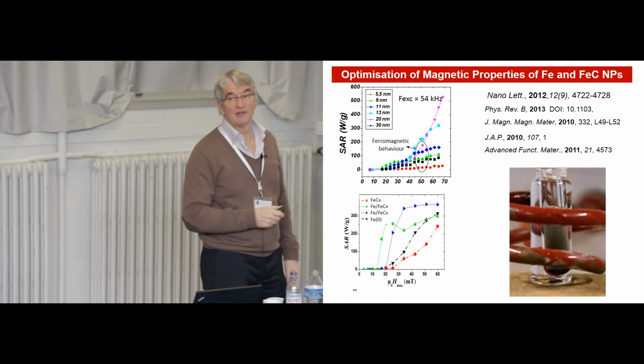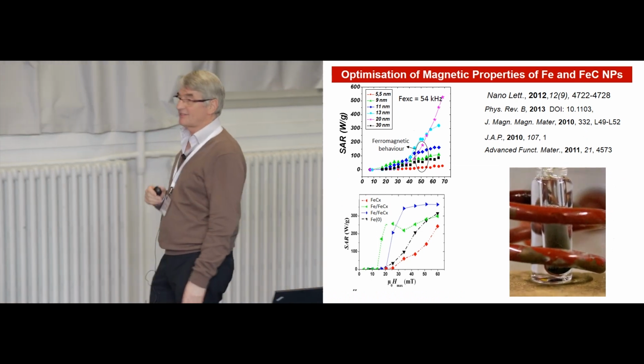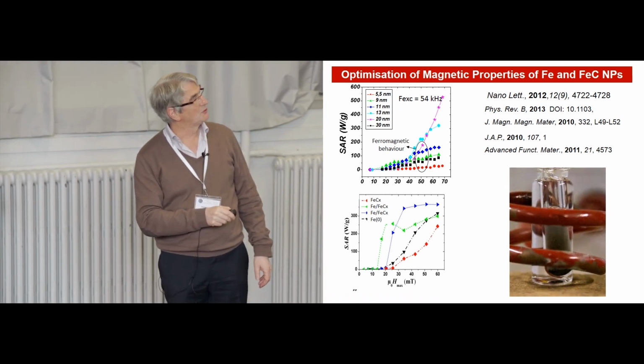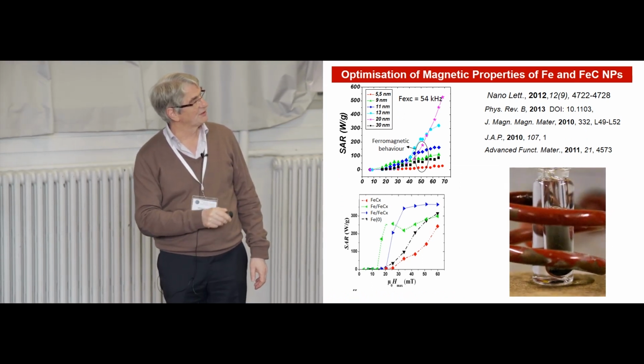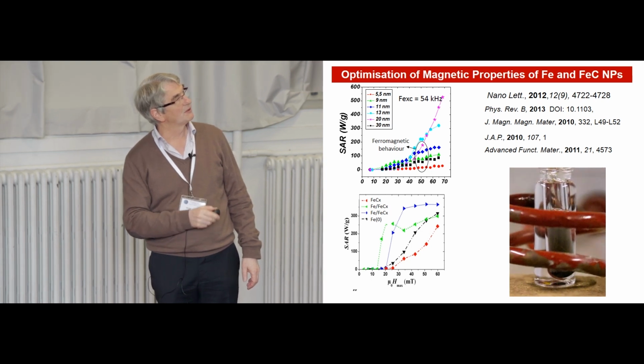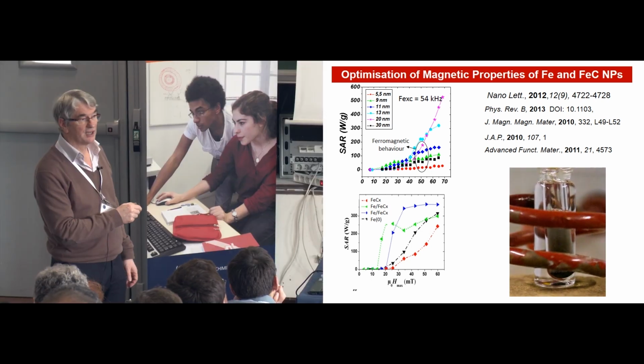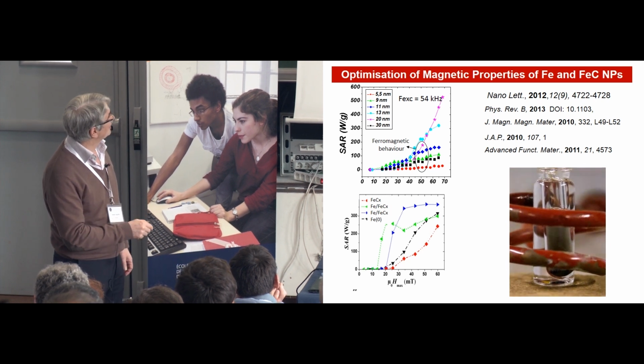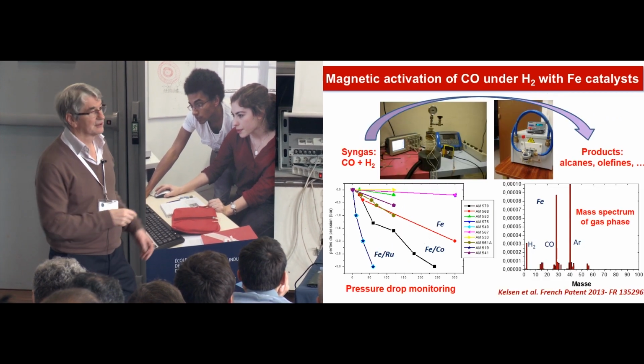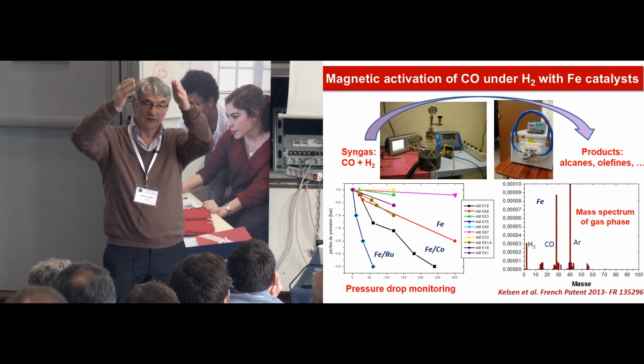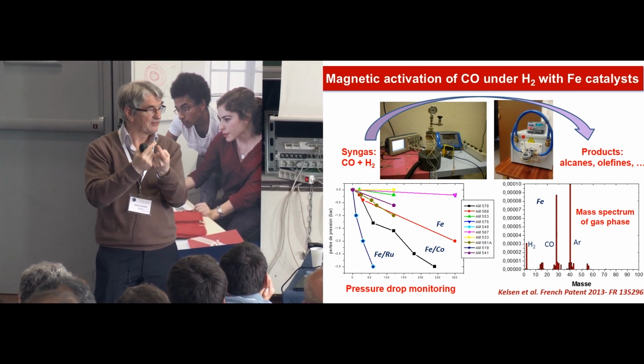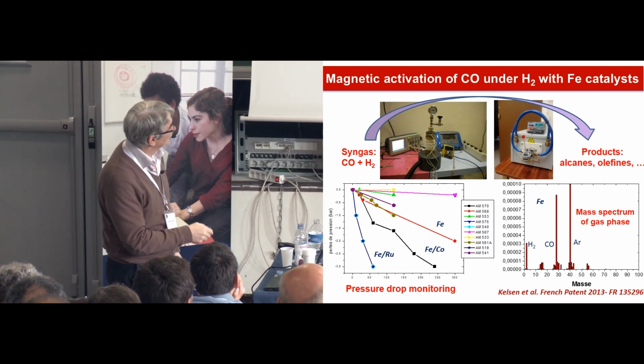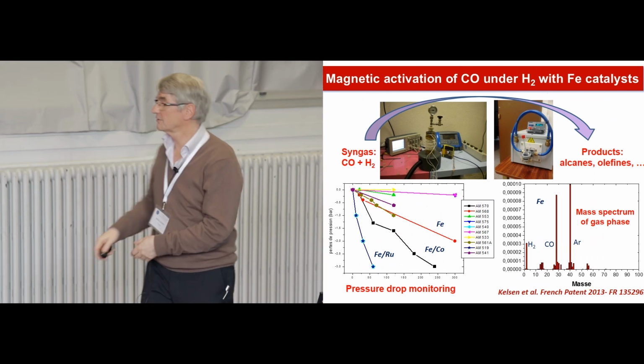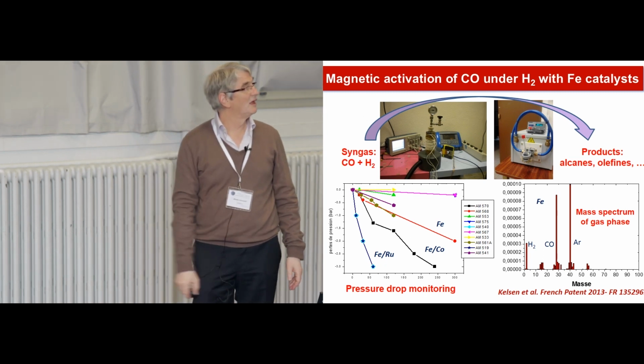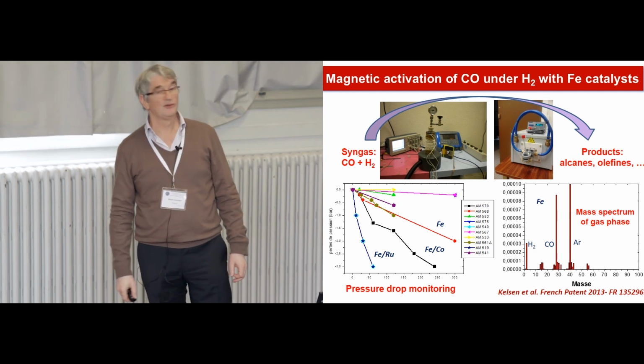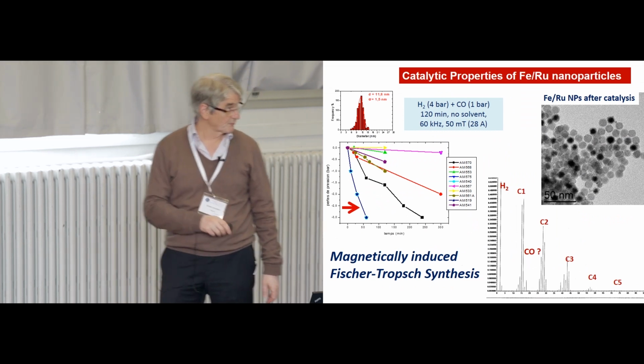And now we will do Fischer-Tropsch magnetically assisted. We can do it with iron, not very efficient, or iron cobalt or iron ruthenium with a marvelous homemade machine. What we see is that if we heat with hyperthermia a mixture of CO and H2 in a vessel, we produce hydrocarbons. We don't see all hydrocarbons, but we produce hydrocarbons. So this is a magnetically induced Fischer-Tropsch synthesis.